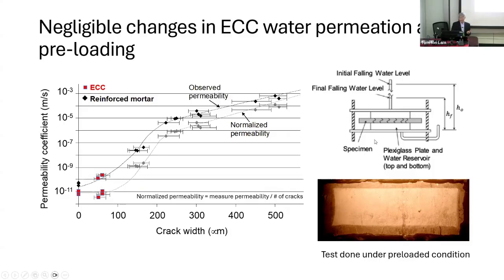Okay, so if you ask what's going on, why is that the case? If you look at the permeability measurements, you actually get ECC at very low permeability despite the preloading of the specimen, put it in tension, and then expose it to a hydraulic pressure and measure the permeability. You see that the ECC is all in the low 10 to the minus 11 meter per second, compared to concrete, which can have all different kinds of crack widths. And then you see the permeability going up really fast. This is not a linear axis. This is a log axis, right? Every unit is a 10 times, 10 times, 10 times jump. It's going up very, very fast. And that explains what I just showed you a moment ago.